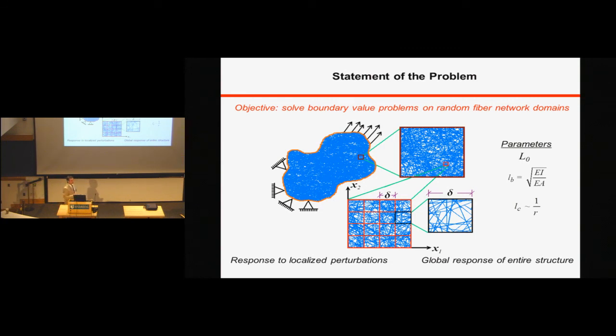So LC, the mean segment length, is a geometric parameter, of course. It depends on the density as I described. LB is a different type of parameter. You notice that it's a ratio between the bending stiffness of fibers, EI, and the axial stiffness of fibers. So it basically tells me whether these fibers are stiff in bending or floppy in bending relative to their axial stiffness. In the following discussion, we are going to play with these 3 parameters to learn a little bit more about the physics of the formation of this material.